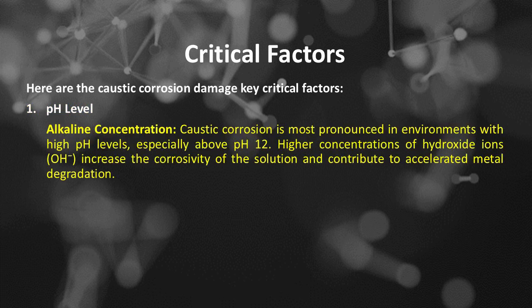Number 1 is pH level. Alkaline concentration. Caustic corrosion is most pronounced in environments with high pH levels, especially above pH 12. Higher concentrations of hydroxide ions, OH, increase the corrosivity of the solution and contribute to accelerated metal degradation.